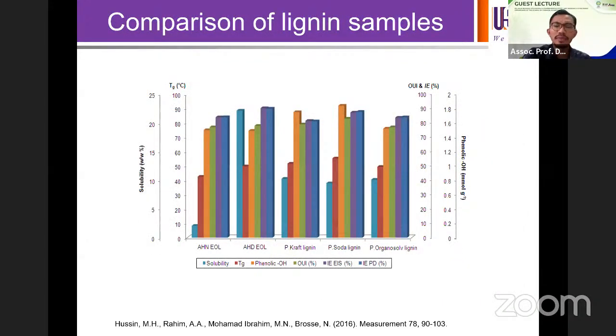So in comparison between the lignin samples, we understand the correlation between modified lignin properties and anti-corrosion properties: if you modify the structure of lignin, it improves in terms of antioxidant activity. When you have a good antioxidant, it means that it will be a good candidate for a corrosion inhibitor, because the corrosion process is basically an oxidation process. And if you add an antioxidant, this will retard or reduce the oxidation process.